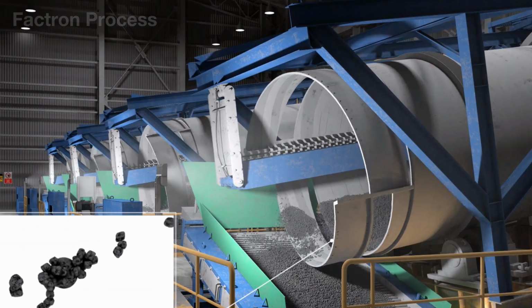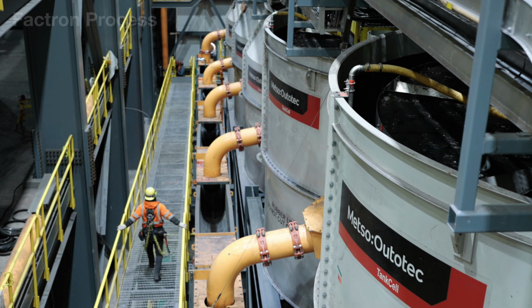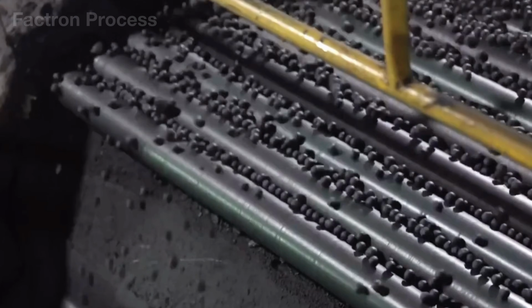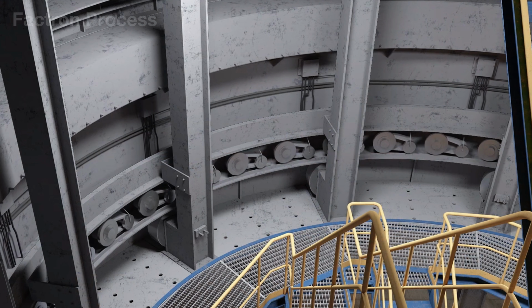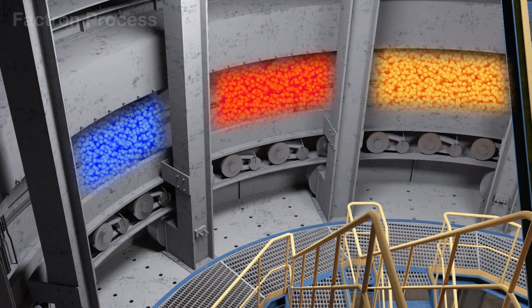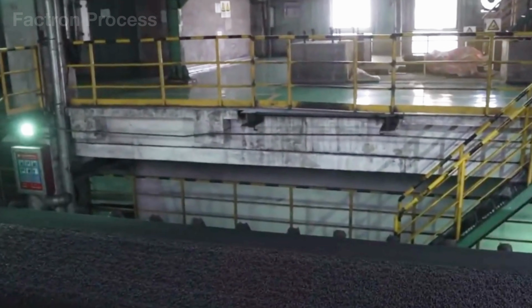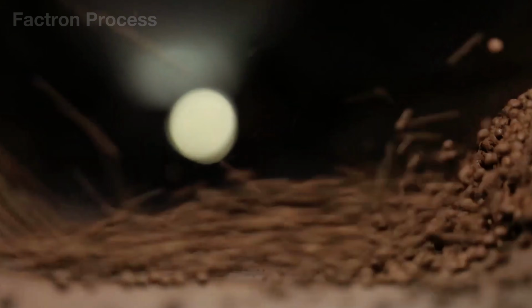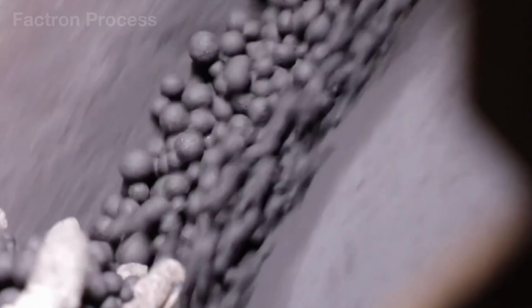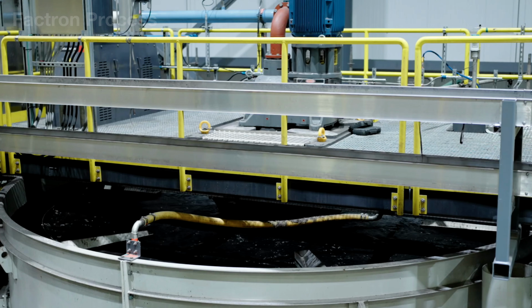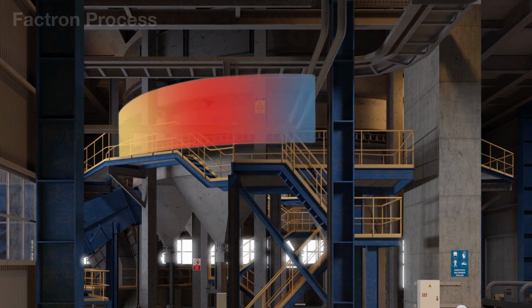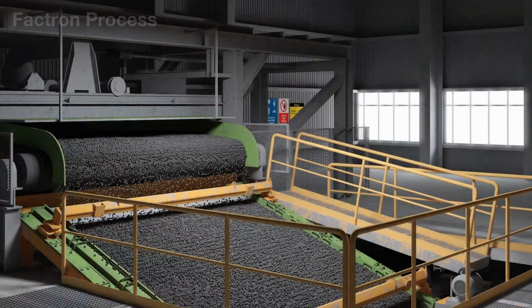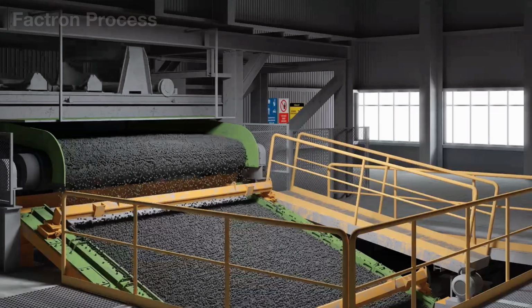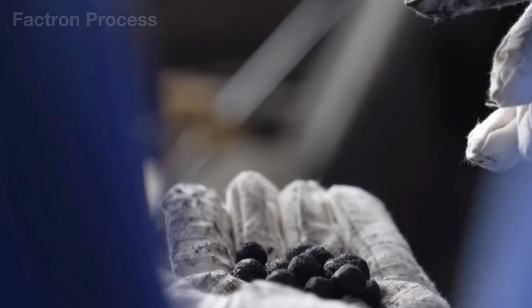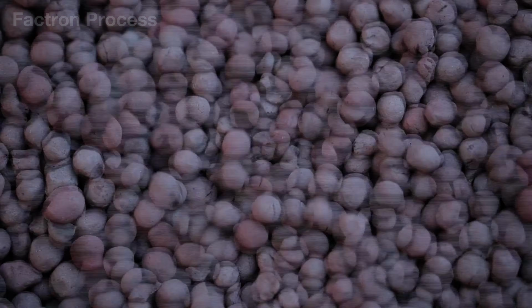to 0.63 inches. Qualified pellets are gradually dried, hardened at approximately 2,280 to 2,460 degrees Fahrenheit, and cooled under controlled conditions. They are then charged into a Midrex vertical shaft furnace, where hydrogen and carbon monoxide-rich gas flows upward from below, removing oxygen from the iron oxide without melting the metal. The final product is sponge iron, or DRI, with a metallization rate above 92%. It retains its spherical shape, but becomes porous like a sponge, ready for refining.